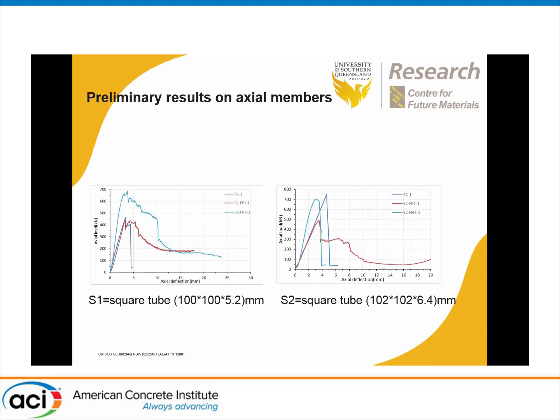The test has been done, and the initial result shows, yes, when you have certain filled concrete, we get a much better behavior. And in some of these cases, depending on the type of cementitious material we are using and the post peak behavior, it also is interesting to note where this is the hollow core one, and this is with filled, and this is with further filled, and different stiffness and different strength, where you can sustain certain load, and around 20 to 30% in some cases, sometimes at around 50% of the ultimate peak load has been sustained and continuous, and basically we can't fail it. It fails at much larger deflections or axial deformations.